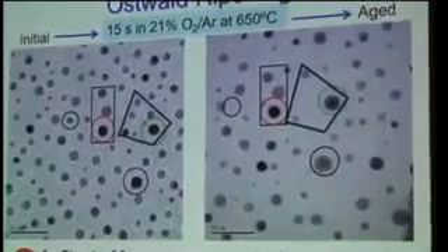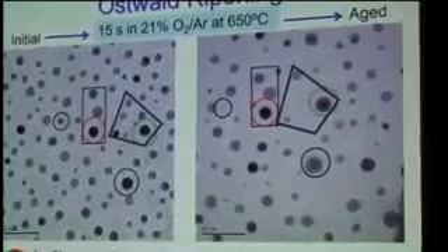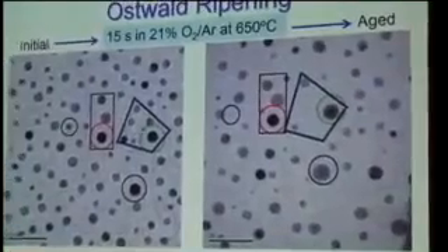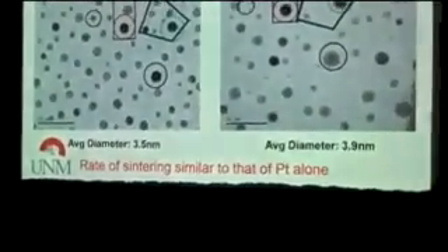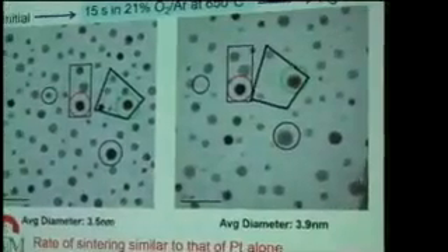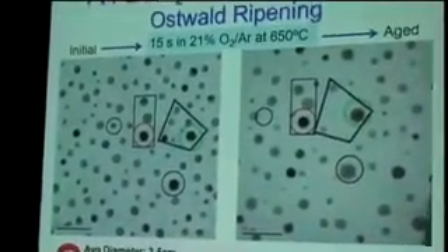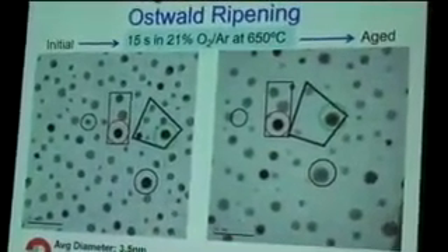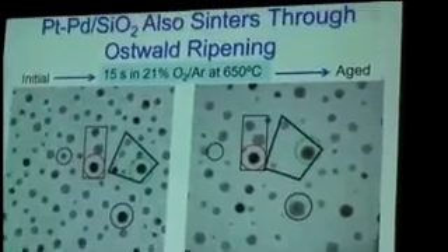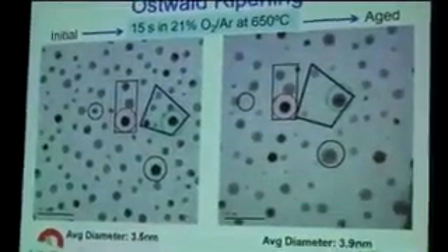Now what about platinum palladium? You see exactly the same phenomenon. So if you cut this box, look at this one here, some particles completely disappear, others are grown in size. So the mechanism is the same. You know that platinum forms a mobile oxide. What about palladium? Can it also migrate? These results show that yes it can. Both palladium can migrate on the surface of silicon and so can platinum.